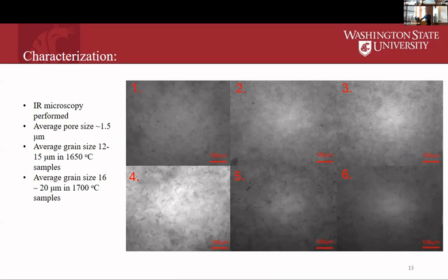The samples sintered at 1700°C had significantly larger grains, but you're also able to see the pores in these samples. In all cases, the pores are approximately 1.5 micron, which relative to the incident light's wavelength is more than enough to cause a very high degree of scatter. We believe that porosity is primarily from the shape and morphology of the particles, the spacing between particles during sintering, and the sintering process not having enough time for material to diffuse and fully close off those pores.